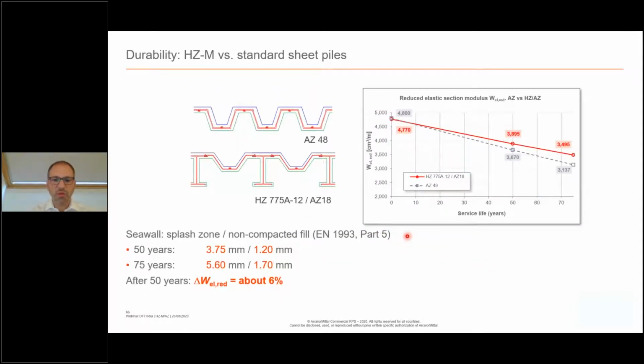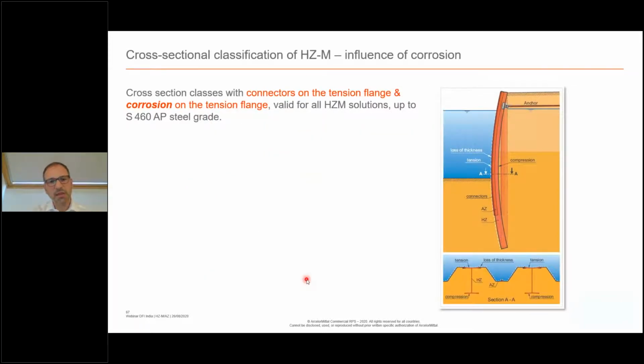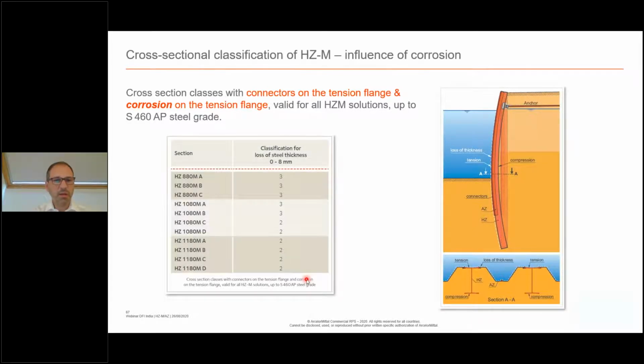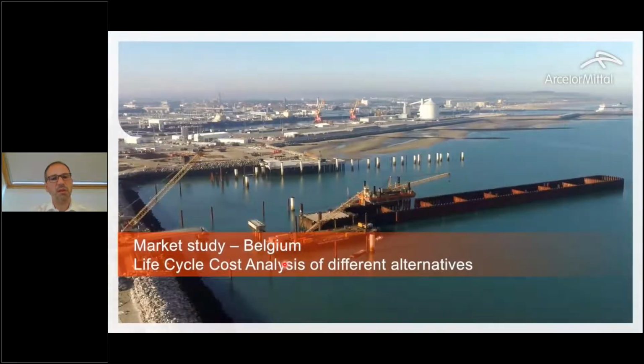And we did this for a specific equivalent solution a couple of years ago. So you see that after 50 years, the difference in elastic section modulus would be about 6%. Now we also analyzed the influence of the corrosion on the classification, and with a loss of steel thickness up to 8 millimeters, it changed the classification of some of the sections. So you see there are more class 3 sections in this table. However, they all stay in class 3, so we don't have any class 4, which is a good thing because then you can use the elastic section modulus even with a corrosion case.